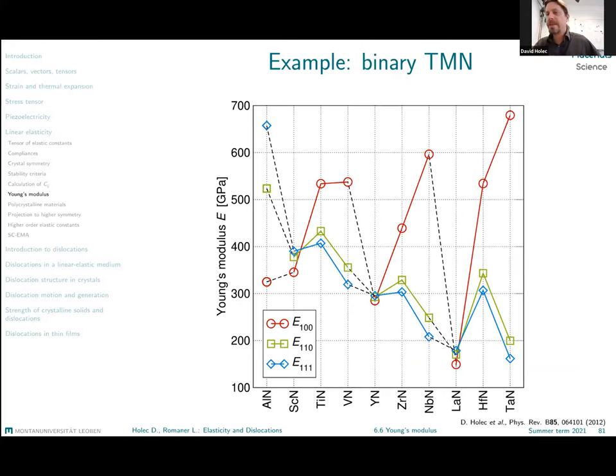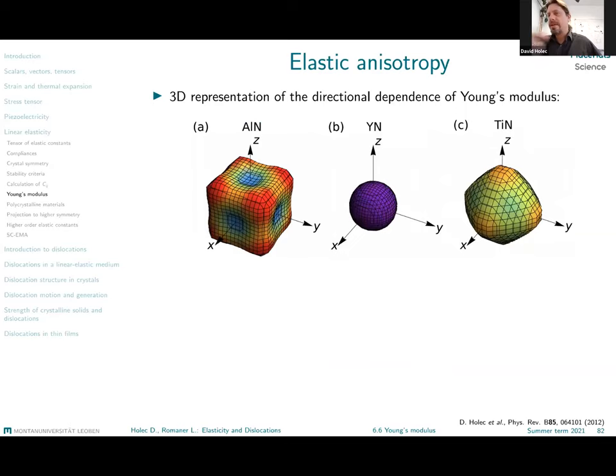This is very often done by such 3D pictures in which the distance from the origin to a given surface, and probably also using the color code, signifies the Young's modulus in a given direction. So for example, for aluminium nitride, and we speak here about the cubic aluminium nitride, we clearly see that the softest direction is along the 100 directions, whereas the stiffest direction is in the 111 directions. The opposite is true for titanium nitride, where we get the stiffest directions along the 100 directions, and the softest ones would be along the 111 directions.